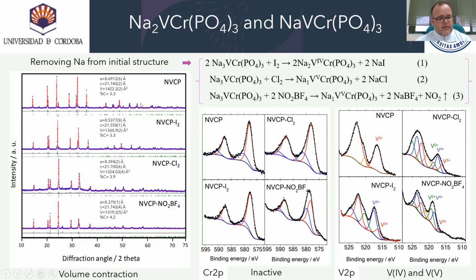If we have a view to the XRD pattern, this sample shows a shift of the reflections to high angles, which is reflected by a decrease of the cell parameters. For the sample treated with iodine, the decrease of the cell volume to 1,361 cubic angstroms involved a cell contraction of 4%. The stronger oxidants, chlorine and NO2-BF4, induced a cell contraction close to 7%, involving a more effective dissociation of the latter.